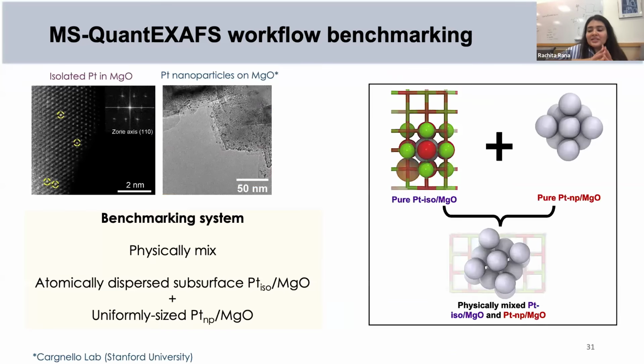All right, so once the code was developed, since the very beginning we've been talking about how to integrate experiments and theory. So the idea was we have the code, we have to benchmark it really carefully. Our subsurface platinum on magnesium oxide system was one of the most stable and homogeneous systems for us to benchmark this code. In addition, we needed another species of platinum, and for that we collaborated with Professor Matteo Cargnello at Stanford. His group makes these beautiful homogeneously sized nanoparticles using a colloidal synthesis method. So we had these isolated platinum and these nanoparticles of platinum, both supported on magnesium oxide.